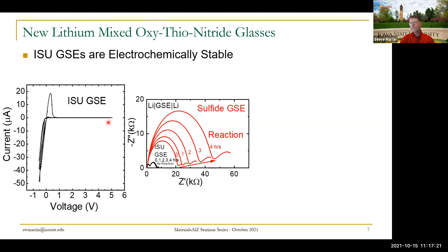Then finally, we also want these to be stable against lithium metal, and that's shown here, where we're looking at a pure sulfide glass, like a lithium sulfide, silicon sulfide glass. We put lithium metal on one side, sandwich it with glass, put lithium on the other side. And you see for that ordinary glass, this is a complex impedance diagram. Just think of it as a resistance. That resistance needs to stay small and not change. If it's changing and getting larger, that means the lithium metal is reducing the glass, producing a parasitic electrode interface that dominates the electrochemical performance. You can see the sulfide glasses react.